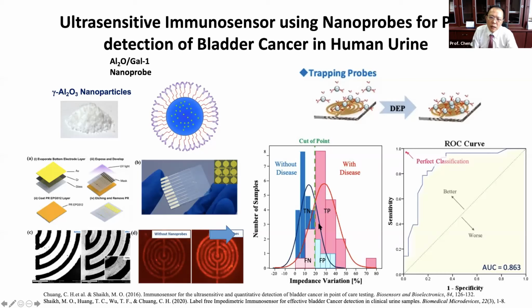We also collaborate with a medical center in Tainan City, Chimei Hospital. We have already tested about 56 patients. We extract each patient's urine and drop the urine onto our sensor, and we can detect the impedance variation. After we collect this data, if we set 20% as the threshold cutoff point, then we can have a very high accuracy. You can see the accuracy goes to 86%. That is the best, and it is better than the commercial test kit product. So this is the bladder cancer work that we did maybe 3 years ago.